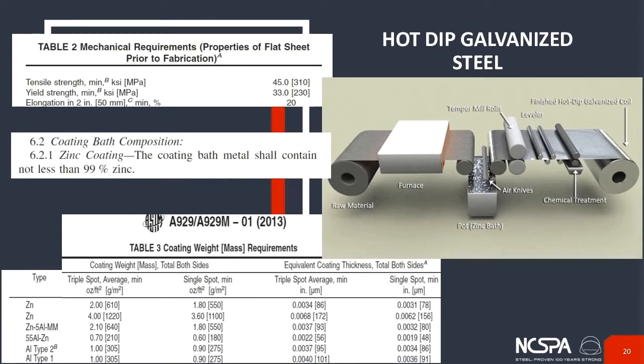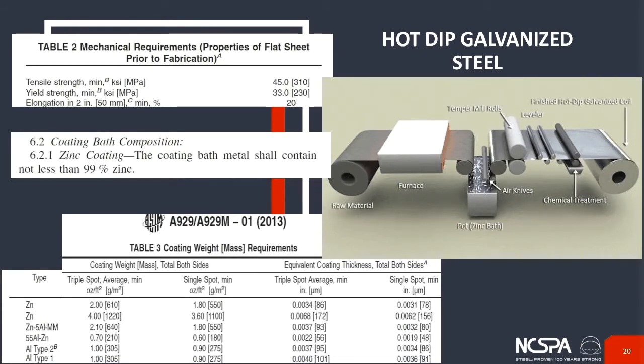So as you can imagine, the process kind of in your head as to how you would coat steel. That picture on the right shows it starting on the left with a black steel coil that's heated, and literally goes through a molten bath of pure zinc. And in the center there, you can see a call out called an air knife. And it's actually air knives, and it's super fast air blowing on each side of that coil to smooth out the coating and make it nice and level and clean. And then it, of course, is coiled up on the other end as the finished coil that you saw on the first or second slide that I showed you.